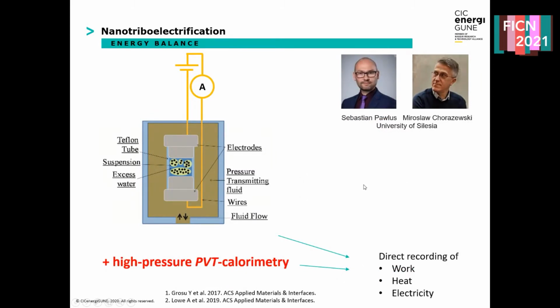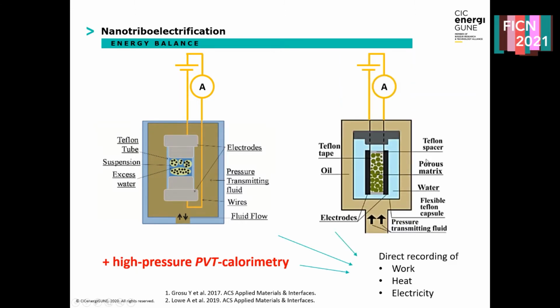So this is the simplified setup we used for that. We tried to measure work, heat, and electrical charge during the intrusion-extrusion process simultaneously. That was a bit tricky to do, considering that we typically work at pressures up to 500 bars and sometimes more. This work was done in collaboration with Sebastian and Miroslav from University of Silesia. We used several configurations to check the results by putting electrodes in different configurations.